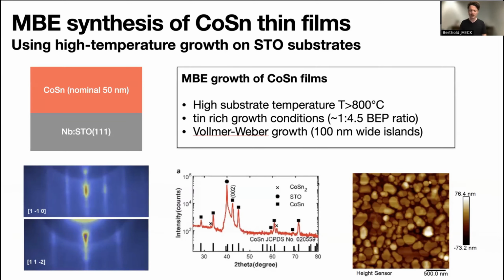It's also worth noting that there are many other phases existing in the phase diagram. So while we can detect a relatively strong cobalt tin phase in some samples, like here, we can also detect other phases that may be a little bit of a nuisance. In any case, for conducting STM measurements, as we know, we don't need much. We just need maybe 50 by 50 nanometers, or sometimes even less. So for this purpose, these films are suitable.